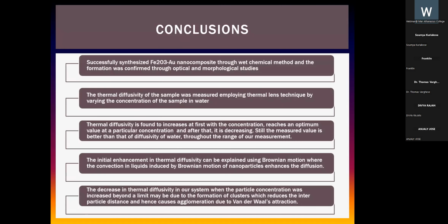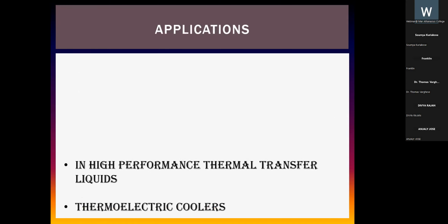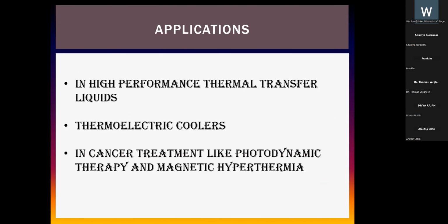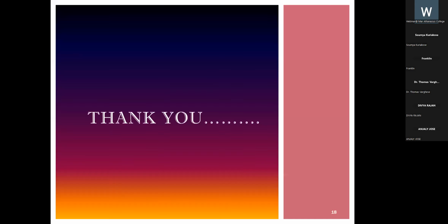Here are the conclusions. We have successfully synthesized iron oxide gold nanofluid composite, and the formation is confirmed through various characterization techniques. The thermal diffusivity study showed a specific pattern of enhanced thermal diffusivity at a particular concentration, from which we can find an optimum value for maximum thermal diffusivity. Here are the applications: in high-performance thermal transfer liquids, in thermoelectric coolers, and in cancer treatment like photodynamic therapy and magnetic hyperthermia. These are my references. Thank you.